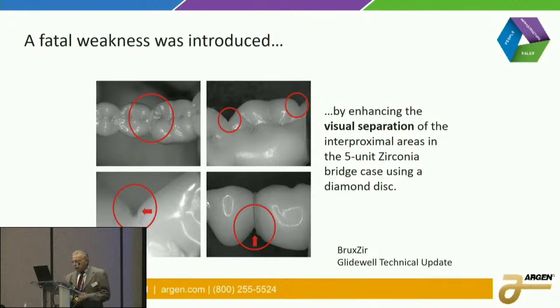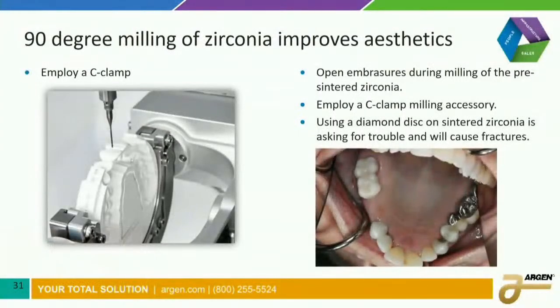And unfortunately, we're still faced with this. Now, in order to improve aesthetics, a couple of companies have come out with this C-clamp, and with the newer software, like the newer SimSystems mill box, you could actually mill at a 90-degree angle and get that separation that you're looking for. Otherwise, you're going to wind up with this. You may notice that there's 2 pontics missing here. Again, they tried to open up the embrasure a little bit, and it just fractured the minute it went into function. So we don't like to see these. No one likes to see these because that means you're going to have to redo the case. But you may want to invest in something like this if you do a lot of long span bridges, because this is going to give you a better aesthetic result than trying to do it yourself by hand. Okay.